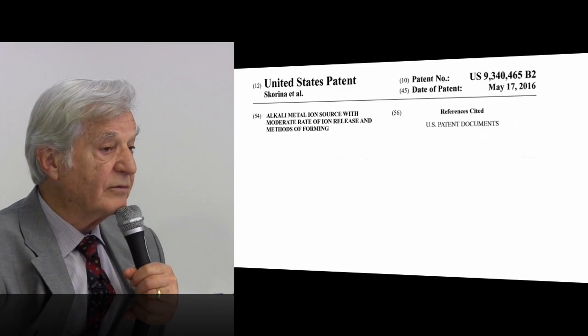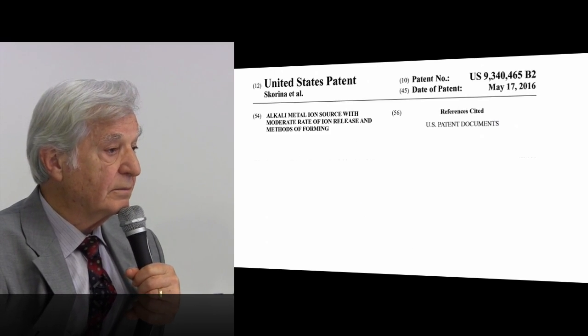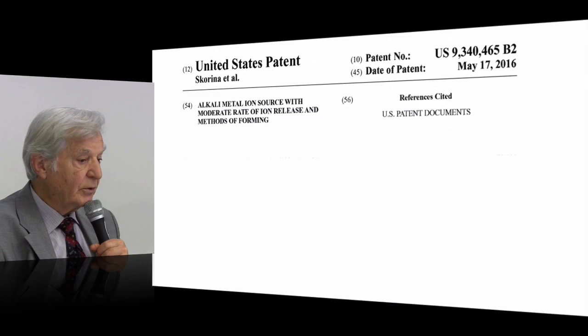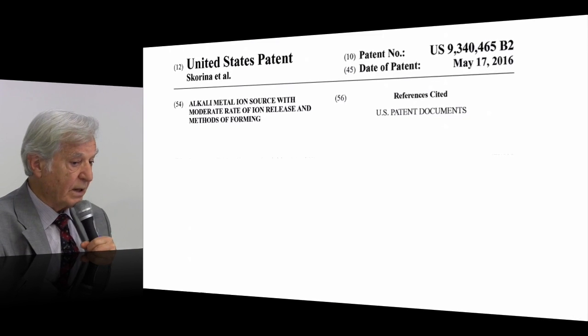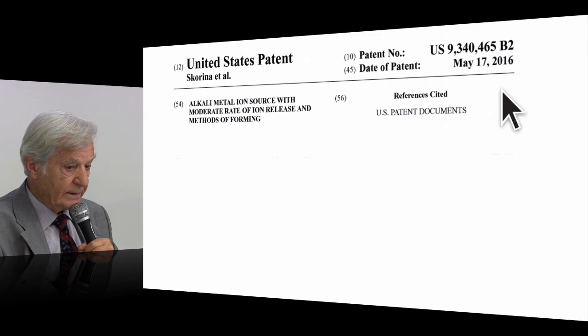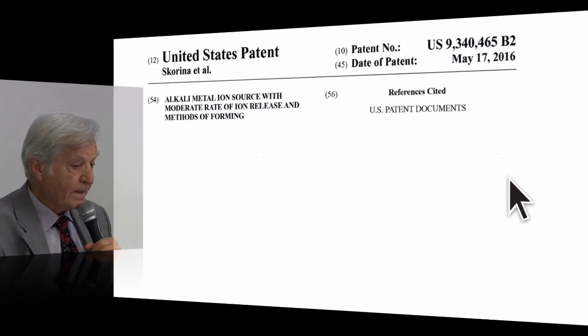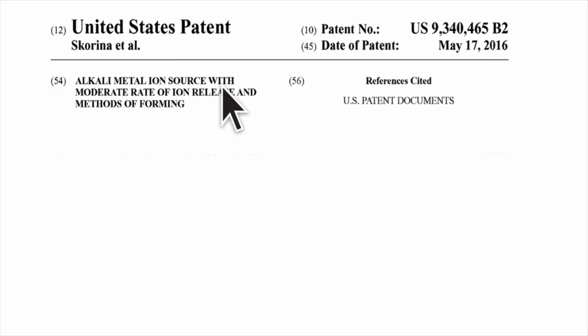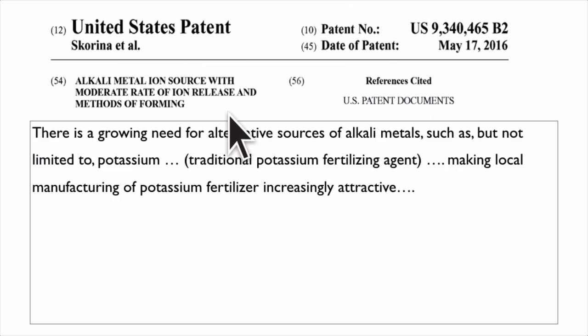So if you want to have a K-ASH and NASH product, you look at one patent that has been granted in the US in 2016: "Alkali metal ion source with moderate rate of ion release." So you extract the cation, the potassium and the sodium, and method of forming.